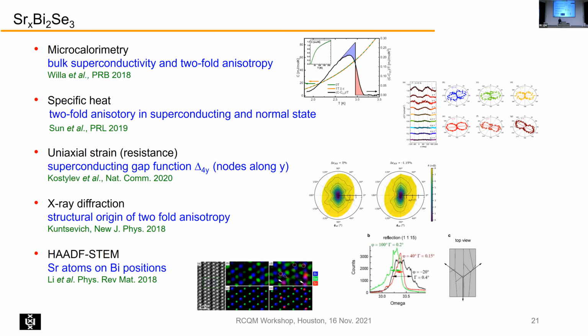First, about bulk superconductivity. It is an issue. We tried very hard to measure the specific heat anomaly at the superconducting transition in the strontium bismuth selenium 3, but it appears that the gamma value is so small. It is somewhere below maybe 0.3 millijoule per mole Kelvin squared. So we have not enough resolution to see the specific heat. So you have to use a better technique. That was done in the Argonne groups. They used microcalorimetry, and here they see a beautiful transition in the specific heat. So this indicates if you have these tiny crystals that they can be bulk superconductors.